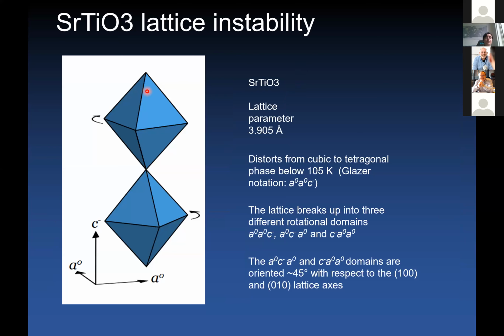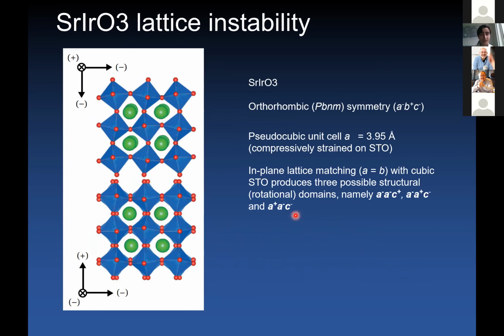In order to understand this point, we need to look at the various lattice instabilities of these two materials. Strontium titanate has this transition from cubic to tetragonal, which is described by an a0, a0, c minus pattern of rotations. So you have one rotational axis along which you have out-of-phase rotations. When you go through this phase transition, your lattice will break up into domains. The domains will be characterized by the direction of the rotational axis, so either along the a, c, or b lattice parameters. The a0 a0 c minus, a0 c minus a0, and c minus a0 a0 domains are obviously oriented at 45 degrees with respect to the 100 and 010 axes.